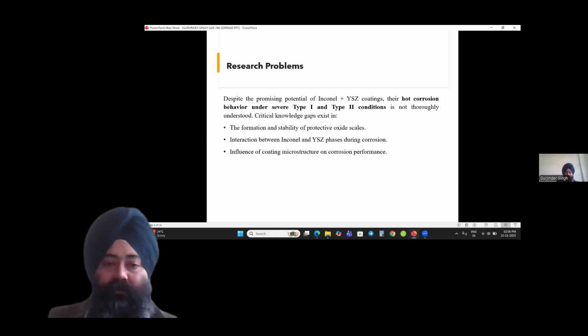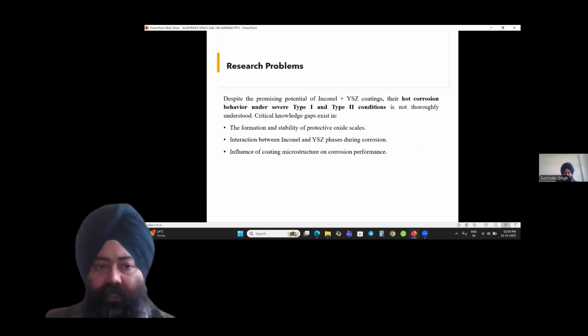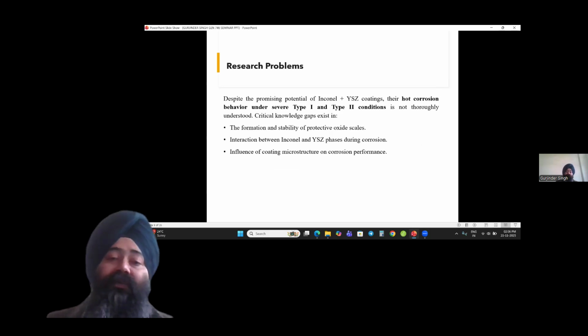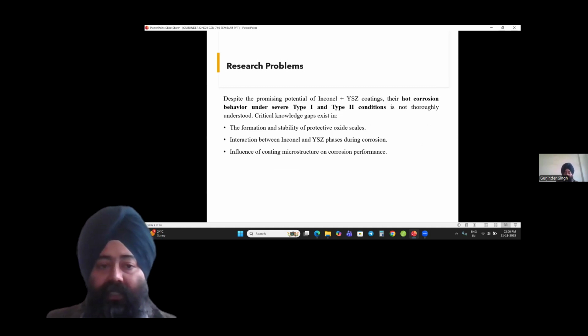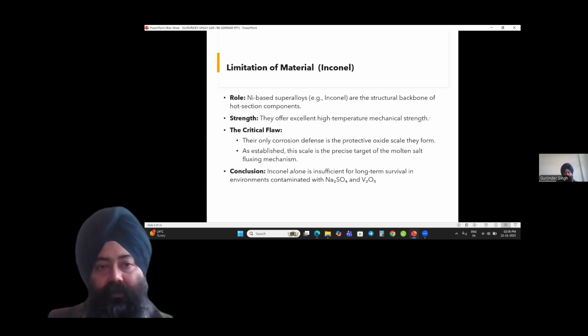Now, what are the research problems? There are some research gaps, or you can say knowledge gaps, that exist in our work. What are the formation and stability of a protective oxide scale after coating? And if we are mixing Inconel and YSZ, what are the interactions between Inconel and YSZ during corrosion? And what is the influence of the coating on corrosion performance? Now, there are some limitations of both materials, Inconel and YSZ. Due to those limitations, they cannot be effective when used alone.